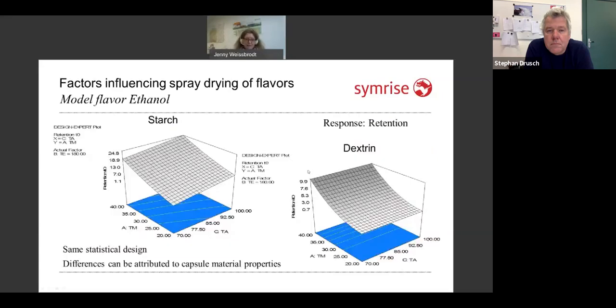So let's look at what happens if I encapsulate my ethanol in these carrier materials. I will just show pure materials in this case. As a response factor, I chose the retention of my actives in the matrix. As variables here, I have the solid content, Tm, and the outlet air temperature, Ta. What you can see for the starch is that there is not a really high impact of solid content and outlet air temperature on the retention of our ethanol. It's comparatively, you just have to believe it, comparatively good retention under these conditions. But there is not a big change with my variables. At the end, a high solid content and a high outlet air temperature, which means a fast drying, give the best results. For the dextrin, it's obvious that only the solid content can save your life.